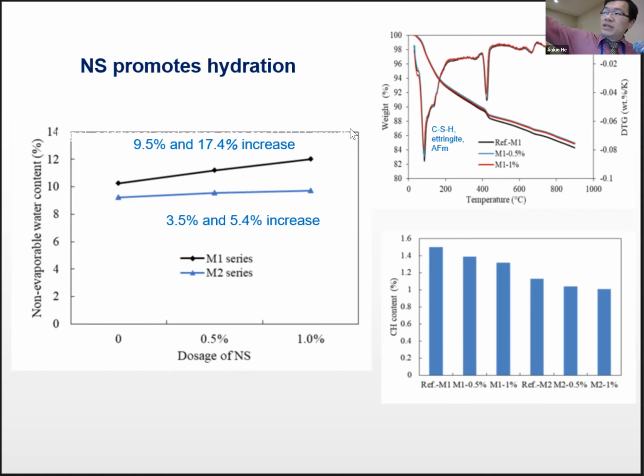And also through the TGA, or thermogravimetric analysis, you can identify how much portlandite, or we also call it CH phase, is in there, which is the peak around 380 to 425 degrees. The area and the peak kind of indicate how much portlandite you have. So when you take that number and plot over here at the bottom, you'll see as you increase the nanosilica, you're seeing a significant decrease in the portlandite because again, they reacted with the nanosilica to form additional CSH gel. And again, comparing with the M1 series, you're seeing less portlandite because you start with a high volume fly ash binder, you don't have as much cement.